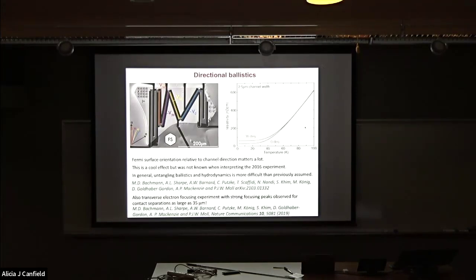And that was incredible because there you're looking at electron focusing in a magnetic field and you're probing it with contacts a certain distance apart on your device. And she could see beautiful focusing peaks with contact separations of 35 microns. So, you know, if you want to do an experiment that makes you believe you have a tens of microns mean-free path, that's the clearest way you can do it. So that was all very nice work too, I think.